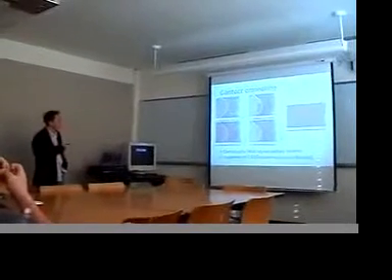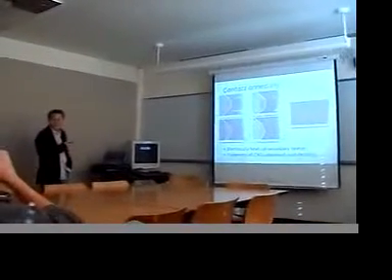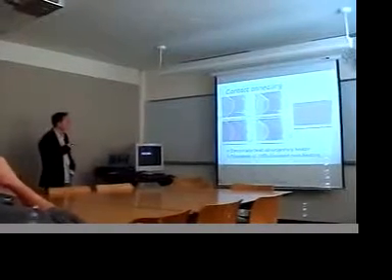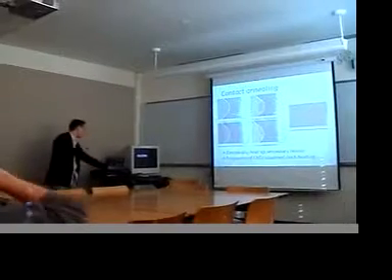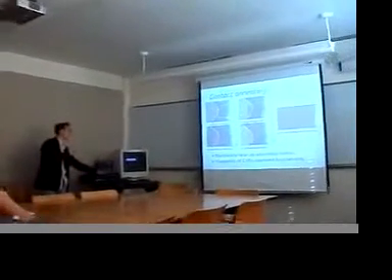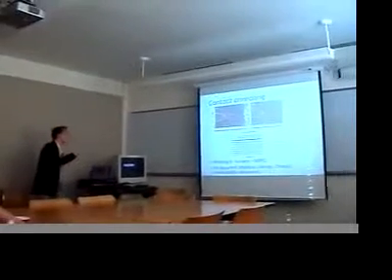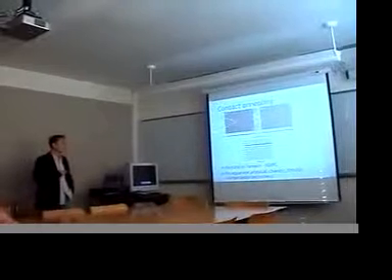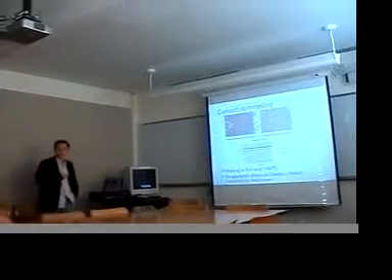You can see a lot of fragments of CNT deposited in the gap. We don't know why that is so. Probably when we did this, we were using too high a temperature or too high a current. So we tried another thing: we put the whole device into a furnace. We did that at around 500 degrees Celsius for 30 minutes.